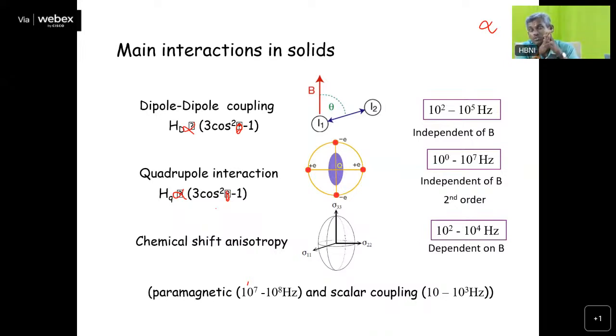So I have also given typical values of this coupling constant, like 10 raised to 2 to 10 raised to 5 hertz for dipole-dipole coupling. And quadrupole interaction has a very broad range, depending upon the environment. For example, if you have a cubic symmetry, an octahedral symmetry, or a cubic 8 coordination symmetry, then the electron cloud distribution is more or less symmetric. So you will have a very low value of quadrupole coupling constant. That is why I have written 10 raised to 0 also. But if you have a completely asymmetric structure, like very poor symmetry, like 3 coordinated or 4 coordinated, deviating from tetrahedral geometry, then in all those cases the coupling constant will increase. Let me go further.